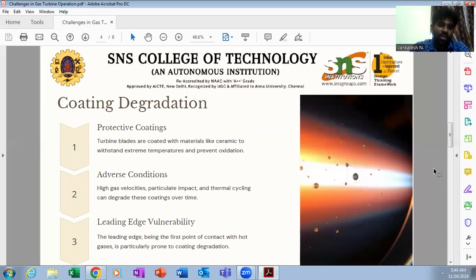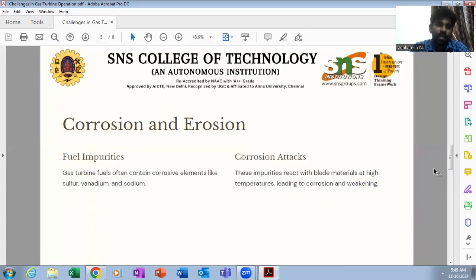Then coating degradation, the protective coating. Turbine blades are coated with materials like ceramic to withstand extreme temperatures and prevent oxidation. Under adverse conditions, high gas velocities, particulate impact, and thermal cycling can degrade these coatings over time. The leading edge, being the first point of contact with hot gases, is particularly prone to coating degradation.